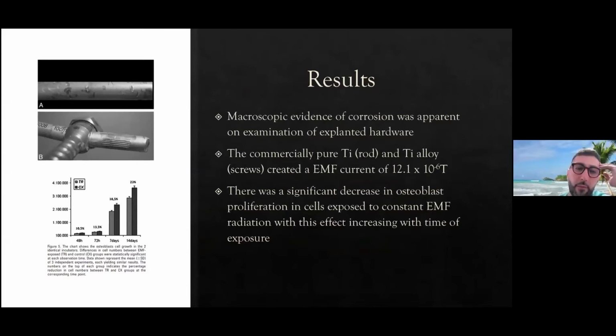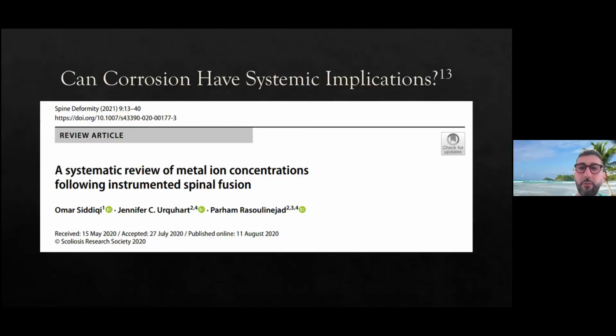And what they found was that when they exposed those osteoblast cell cultures to this current for different periods of time, and I've shown you the time periods here, 48 hours, 72 hours, 7 days, and 14 days, there was a significant decrease in osteoblast proliferation. And that effect increased with increased time from exposure. So again, it's hard to extrapolate these results to every patient. I don't think galvanic corrosion is going to be front and center in our mind in surgical planning, but it is a factor to consider. People talk about it most when you think about mixing and matching metals, and we will talk about that in a little bit as well.